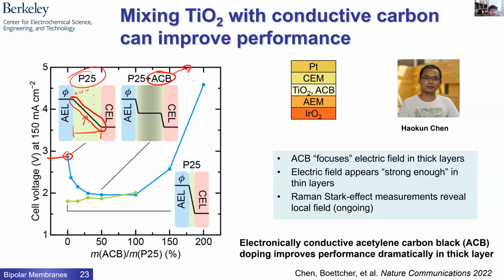Now, this material by itself doesn't do any water dissociation. We've separately shown that. It doesn't have any hydroxyl groups on the surface. There are not very many. So it's not itself driving the reaction. But when you mix it with the P25 and you increase the conductivity of the composite, boom, the voltage to dissociate water dramatically drops until, in fact, it's almost equivalent to the optimally thick TiO2 layer. So the hypothesis from this is that we must be focusing electric fields in a way that gives us sufficient driving force to dissociate the water.